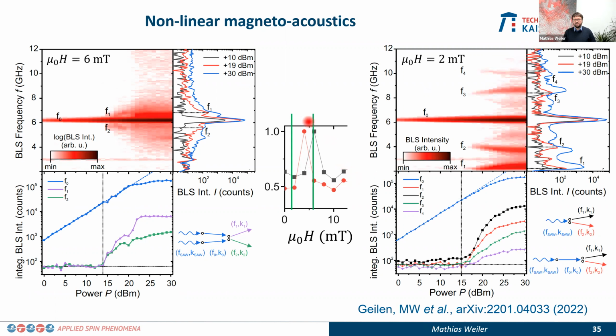One can also go to a magnetic field that is actually below the resonance field, here 2 millitesla, and do the same experiment again. And then what one sees is that one excites, in this case, a whole slew of different magnon modes in a nonlinear fashion. These magnon modes can be described either by a direct pumping by the acoustic wave, or by a process where the acoustic wave is first converted into a magnon in linear fashion, and then we have a nonlinear magnon process. These findings are currently on the arXiv.